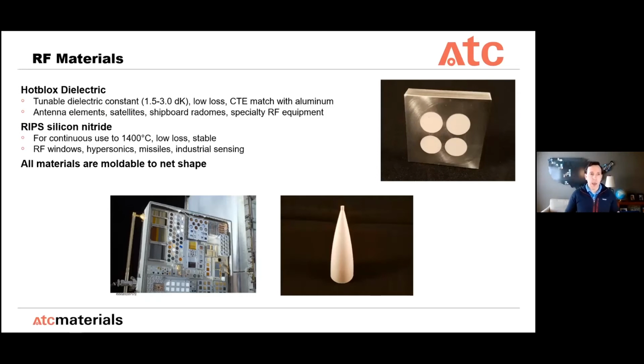So what does that mean? Number one, the CTE match means we can mold it in inexpensive aluminum molds. So that helps the manufacturing process, but it also means that we can co-mold it into aluminum housings or aluminum waveguides. So the picture in the top right, it's about an inch or 30 millimeters on a side. And those four little antenna windows there are the hot blocks material that is molded into the aluminum.